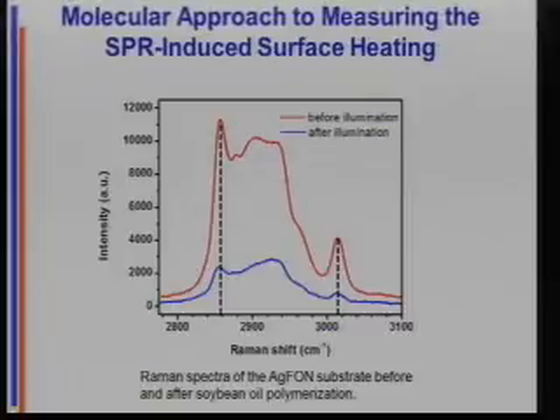So you can bracket it by looking for polymerization. If you paint your substrate with soybean oil, I mean really soybean oil, and you irradiate it, and you take a Raman spectrum before and after. If you think about polymerization of double bonds, you're trading vinyl CH bonds for aliphatic ones, and you can distinguish those in the vibrational spectra. So here we have vinyl CH, aliphatic CH, and the ratio changes after irradiation, and soybean oil begins to polymerize at 230 C.